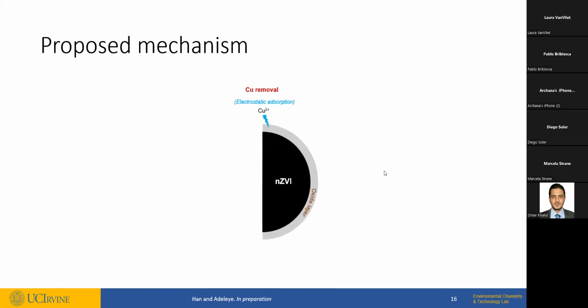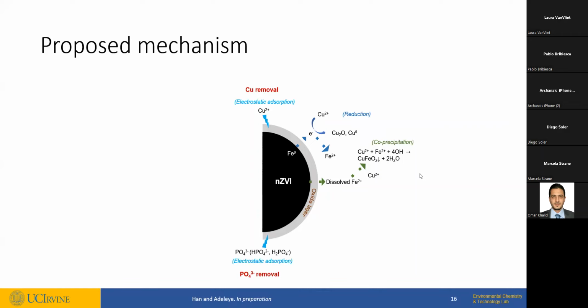So for the removal of copper, we think that adsorption is occurring because of electrostatic attraction. I also showed you already that there is reduction of copper 2 to copper 1 and 0, and that leads to the production of Fe2+. Okay, and there is also dissolution of Fe2+. So not all of it, some of it goes to co-precipitation. So we have this precipitate formed, and on the phosphate side, there is also some surface adsorption. There is surface complexation. We confirm this via MINTEQ modeling, but the most interesting reaction is the reaction between Fe2+ and phosphate, which leads to the precipitation of iron 2 hydrogen phosphate.